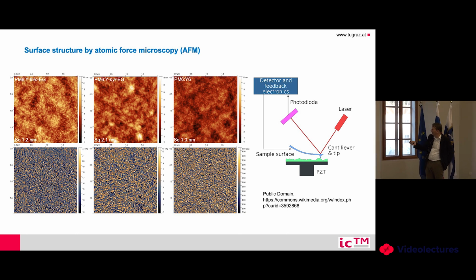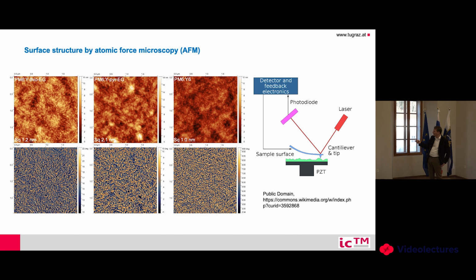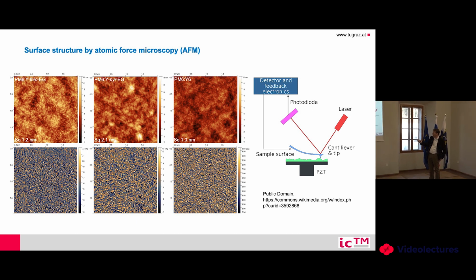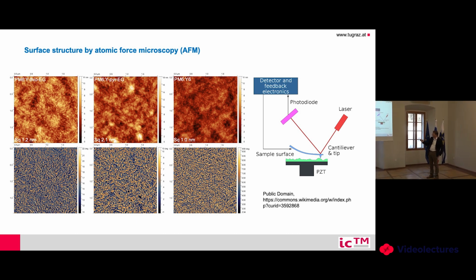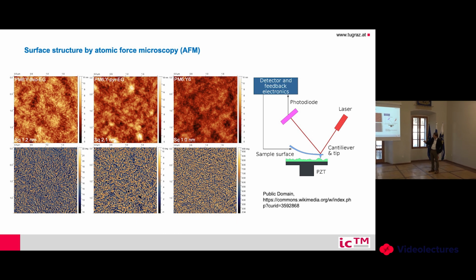And actually you see here the surface morphology of all the different materials. So this commercial one, but also our synthesized material, they look a little bit different, but if you look at the scaling, it's very similar. It's not explaining everything, especially here. This is the so-called phase image, because you see a little bit of the chemical structure, I would say, or physical structure. They are very, very similar. You don't see very large issues. So this could not explain why you have these large differences.